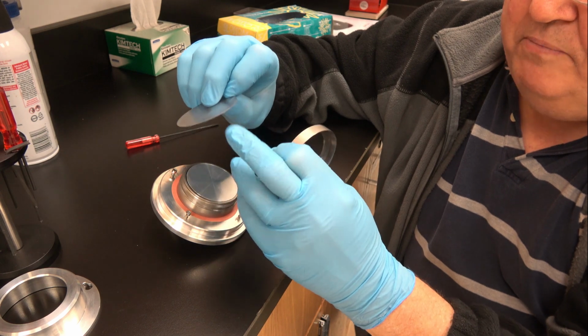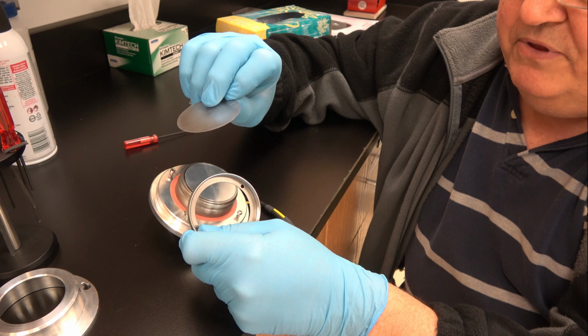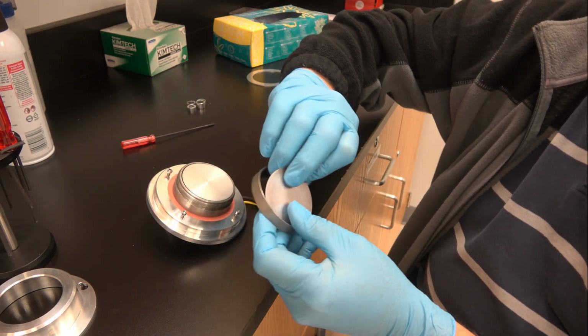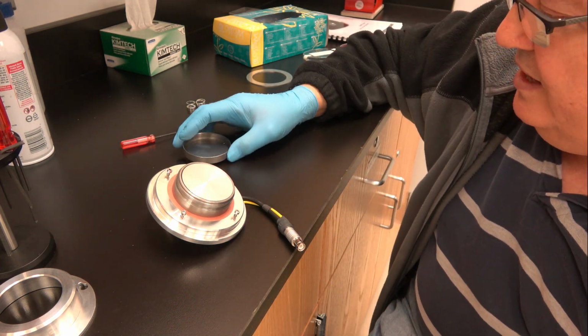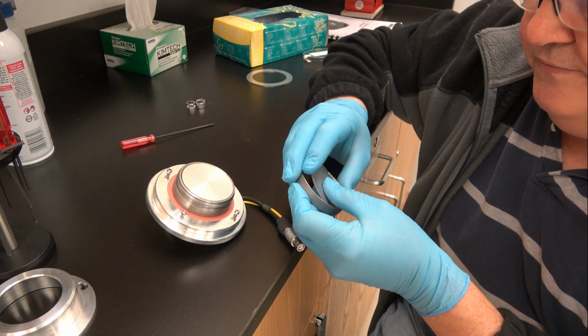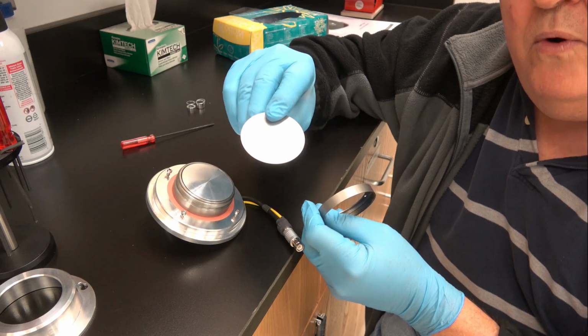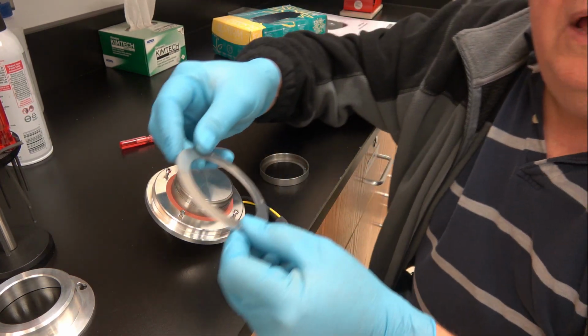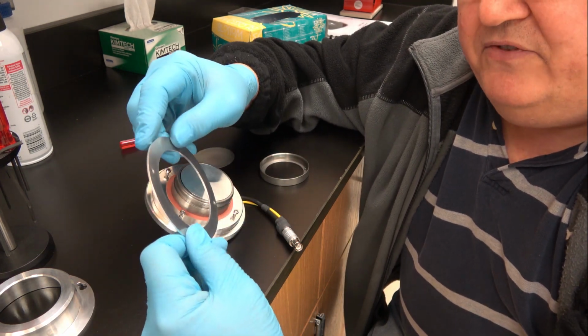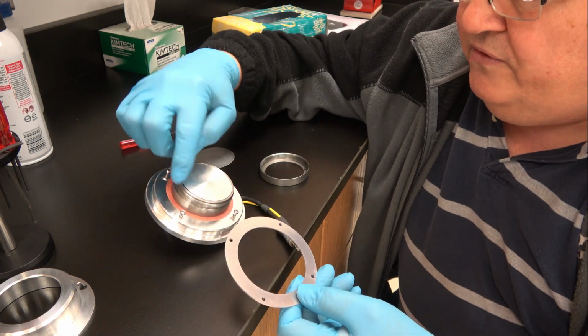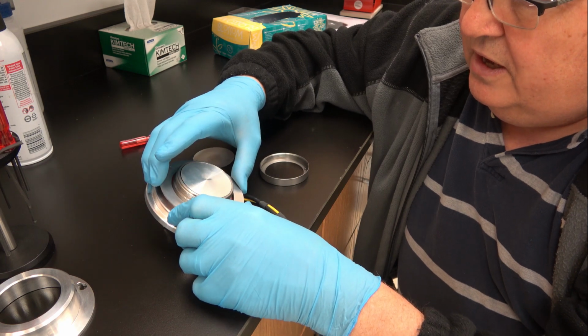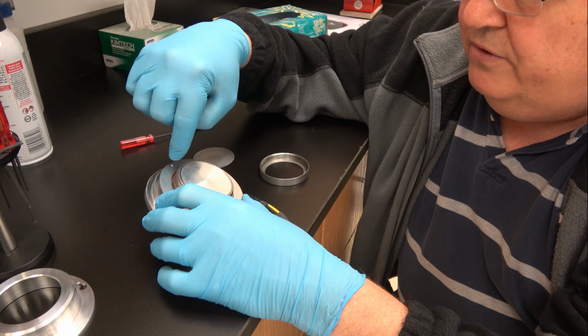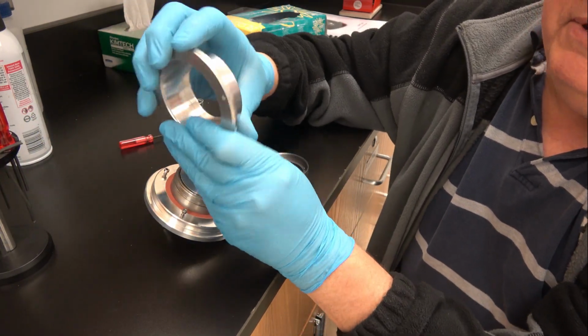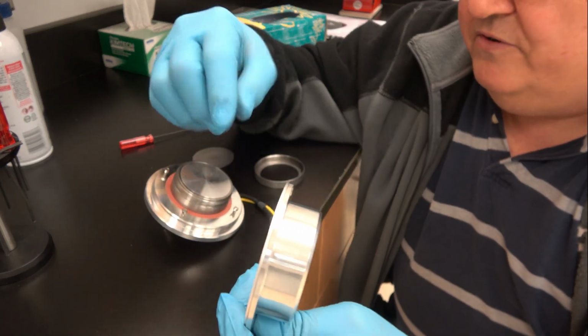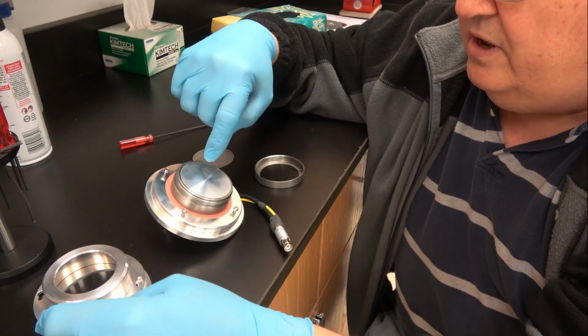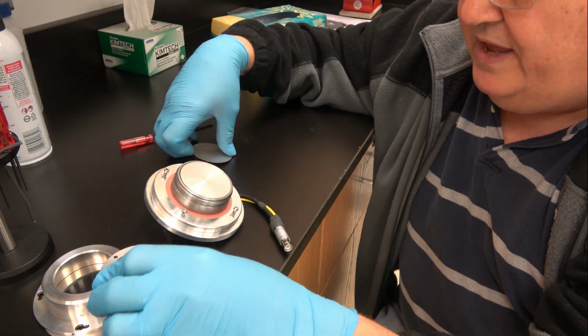So the target is typically 0.1 millimeters thick. They could be up to 3 millimeters thick. One of the problems which I encounter quite frequently is somebody wants to use a thicker target. If you use a target thicker than 0.1 millimeters, you need to install this target dark space ring spacer. That's installed by removing these 4 screws, placing this on the sputter head, putting the screws through it, and this raises up the spacer by a couple of millimeters, preventing the sputter head target retaining ring from shorting out to the dark space ring.